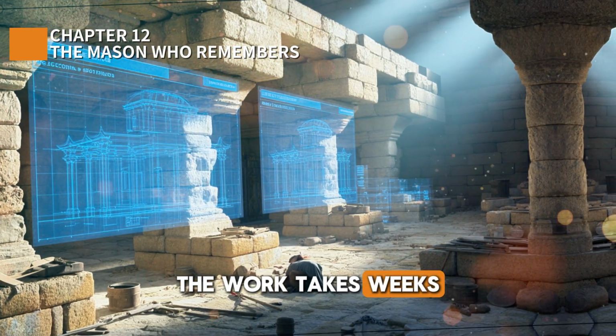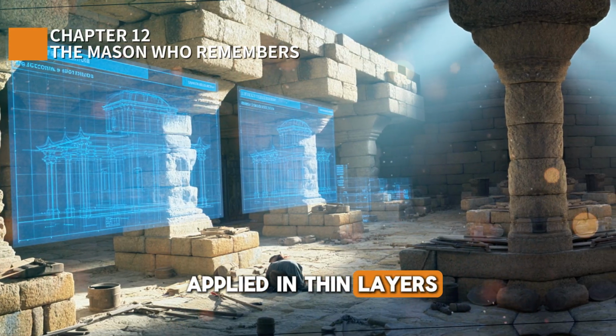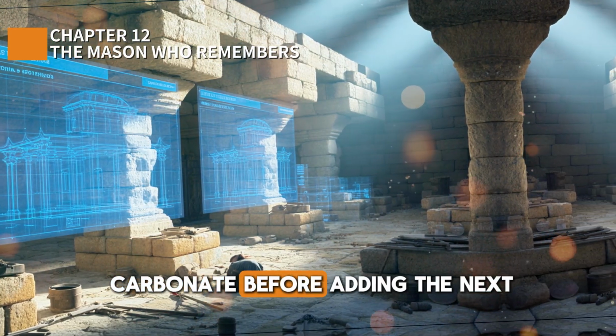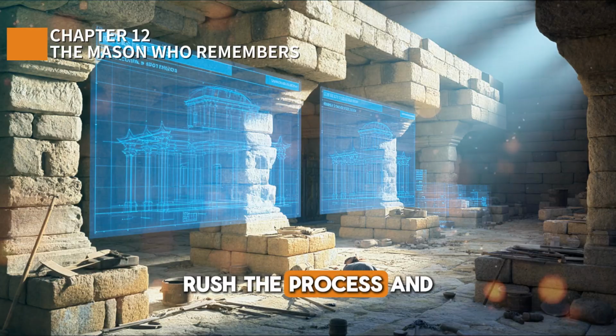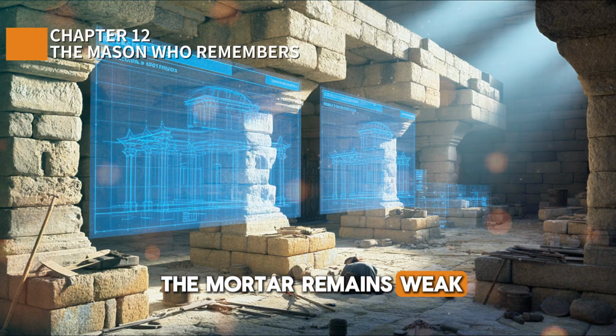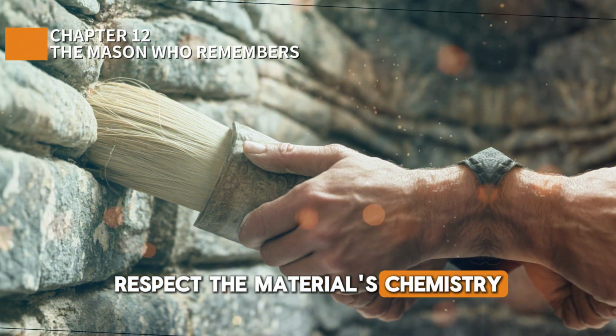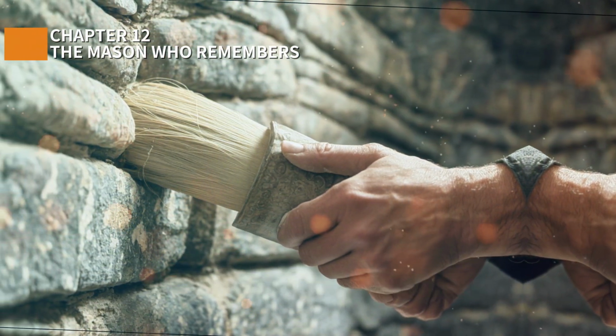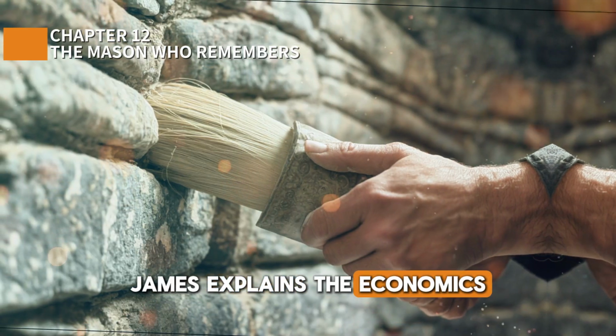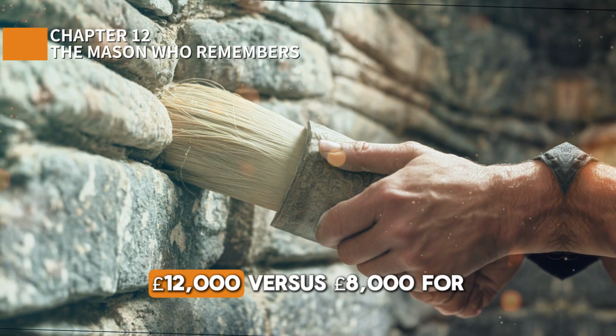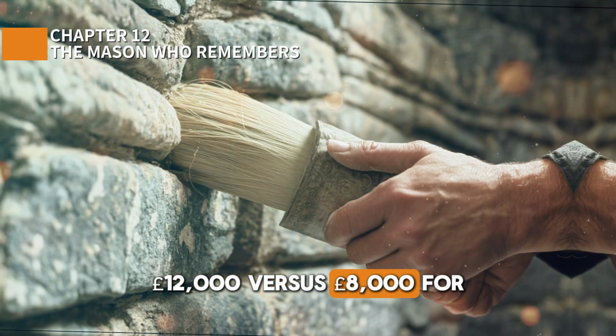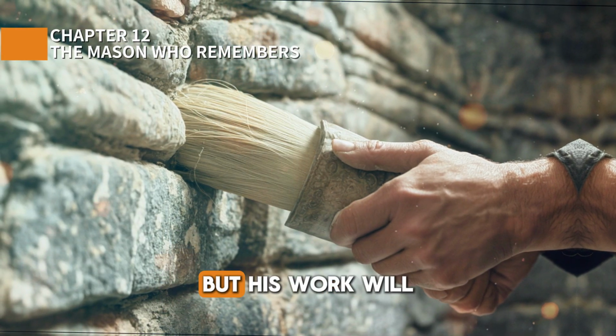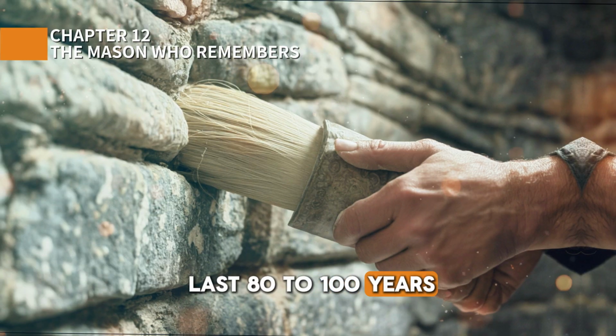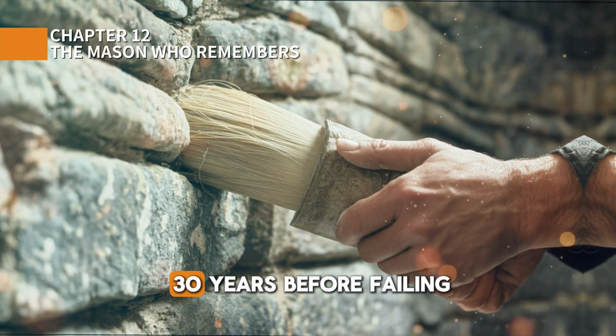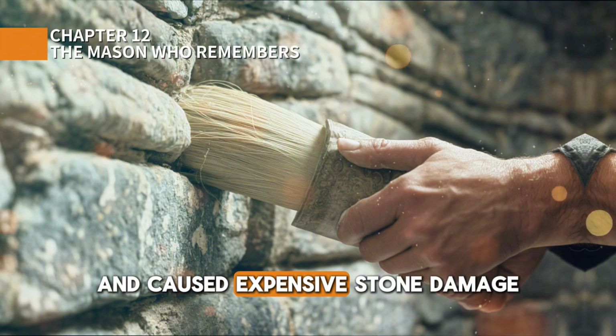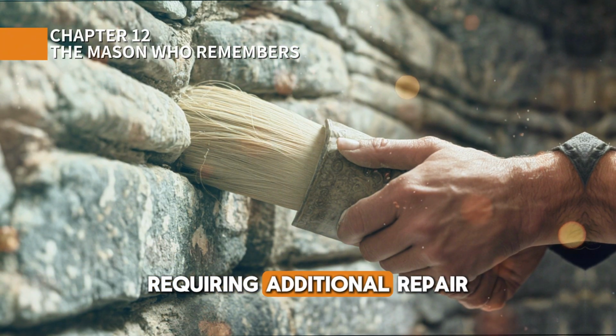The work takes weeks. Lime mortar must be applied in thin layers, allowing each layer to carbonate before adding the next. Rush the process, and the mortar remains weak. Respect the material's chemistry, and it performs beautifully. James explains the economics. His repair costs £12,000 versus £8,000 for cement repointing, but his work will last 80 to 100 years. The cement repointing lasted 30 years before failing and caused expensive stone damage requiring additional repair.